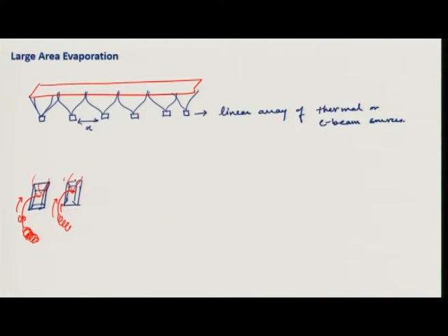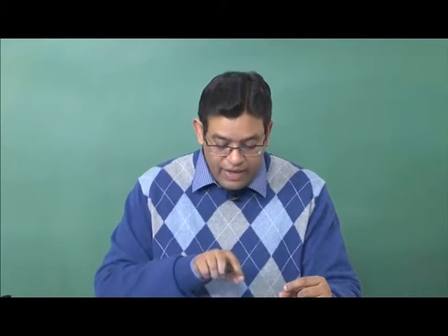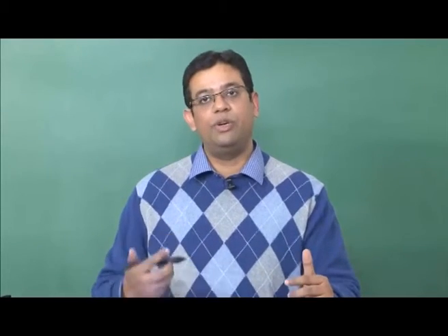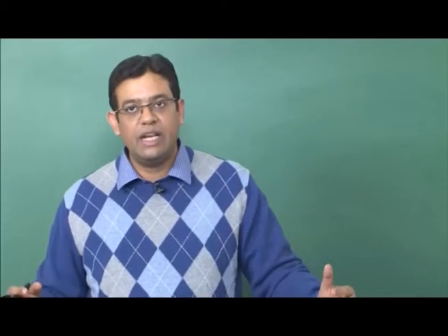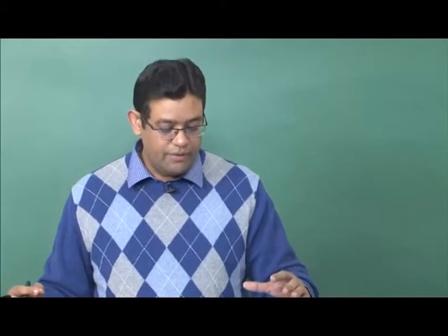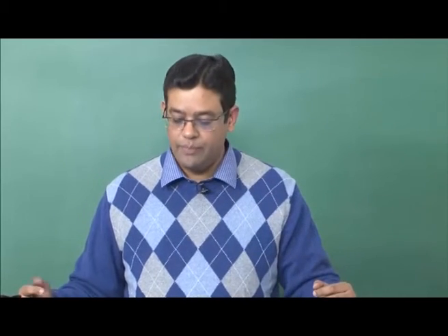Now, you can have very small size of these boats. You do not need to melt this entire spool of the material, you are only melting very small amount, and you are feeding this as per your deposition rate. So, these kind of wire fed boat systems are normally used for very large area deposition in thermal evaporation.